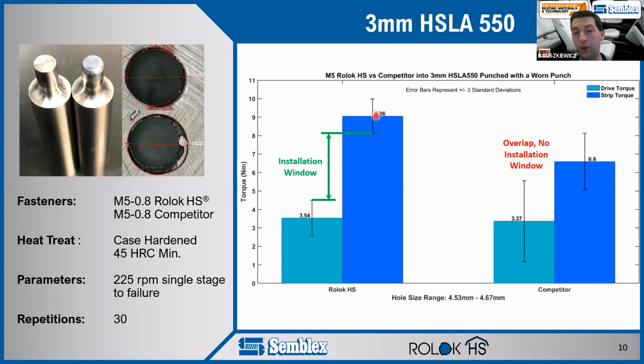So our failure or our strip torque, the dark blue bar, is coming from the larger hole size. So essentially, we're showing the data across the entire range in the worst case scenario. So we have the highest drive torque with the lowest failure torque that you're going to see from this application. If we look at the competitor, remember we want a nice big gap between that drive torque and that failure